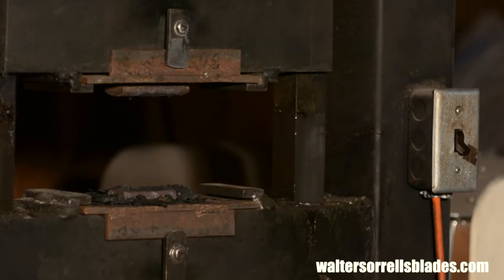I do recommend preheating your dies though. Just stick a piece of stock in the forge, get it red hot, then close up the jaws of the press and it'll absorb the heat. This way you're sucking less heat out of the outer layers of the steel, making it weld better.